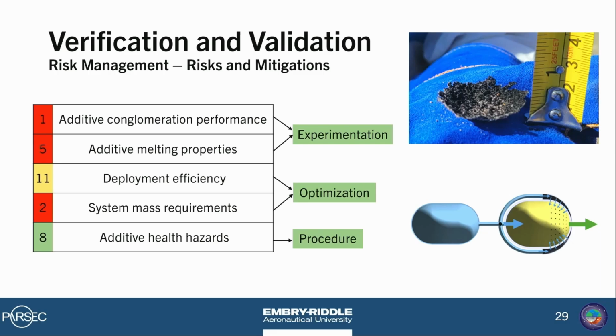While we had documented this risk earlier on in the process, this risk became more apparent during testing because, as Grant mentioned, we did have a case of clogging with the 4 to 7 micron size alumina in the gravity-fed hopper. While this risk for us is mitigated since we'll be using a fluidization system instead of a hopper system, we'll need to further optimize the system to be less susceptible to clogging in the future.